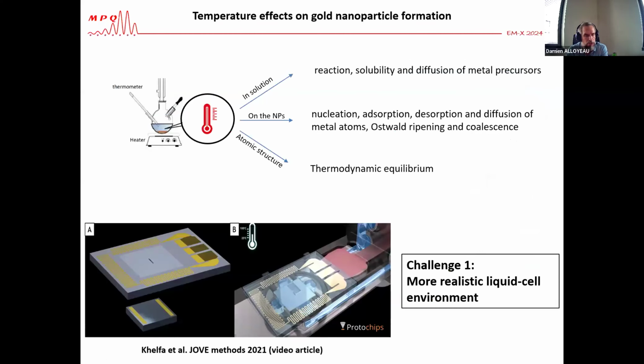Now, I told you that the first challenge that we have to meet is we have to work in a more realistic liquid cell environment. And what we have done more recently is studying the effect of temperature. And actually, temperature is a very tricky parameter because any atomic scale mechanism that is involved in the nucleation and growth of nanomaterials is temperature dependent. In the solution, the reaction, solubility, and diffusion of the metal precursor depend on temperature. On the nanoparticles, the nucleation, adsorption, desorption, diffusion of metal atoms, and also large-scale mechanisms like Ostwald ripening and coalescence depend on temperature. And even the atomic structure, the thermodynamic equilibrium, is also temperature dependent. So you definitely need an in situ probe to distinguish between these different effects.